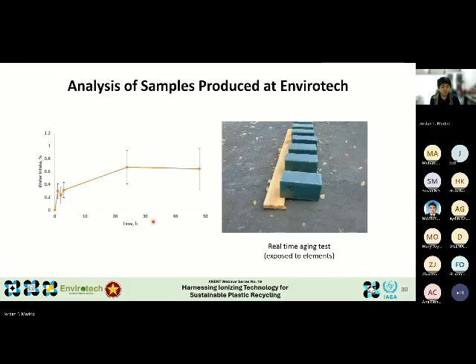Similarly, the samples produced at Envirotech were also tested for water absorption, and just like what we had seen earlier at the lab scale, the calculated water intake, as shown in this plot, remained very minimal. This is important because excessive water absorption can compromise mechanical properties and shorten the lifetime of materials, especially when used outdoors.